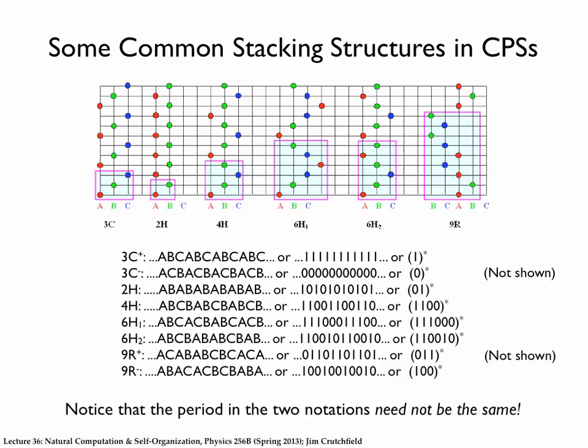And I hope you can see this. So here, the 3C is the same as the FCC, and you can see that I have just the stacking ABC, ABC, ABC, ABC, or in terms of the other notation, the 0-1 notation, which is commonly referred to as the Hägg notation. Typically, in the Hägg notation, they call it plus and minus, but we always just use 1 and 0 because it's much easier to write.